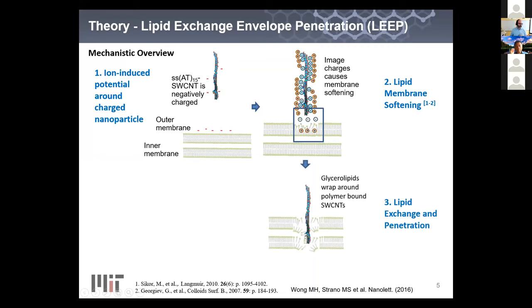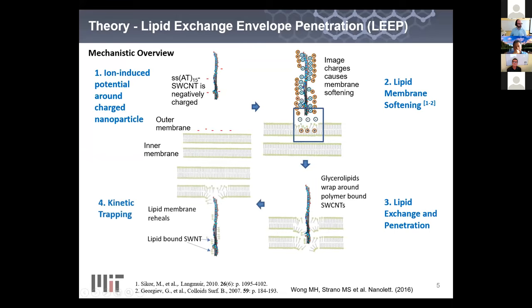What we understand to be happening is that there's a lipid exchange. So the lipid will then bind with unsaturated sites on what's called the nanoparticle corona. And this pulls the particle in, but what emerges on the other side is a kinetically trapped nanoparticle. So it no longer has the driving force to pass back through. That makes the process irreversible. You have to take my word for it.